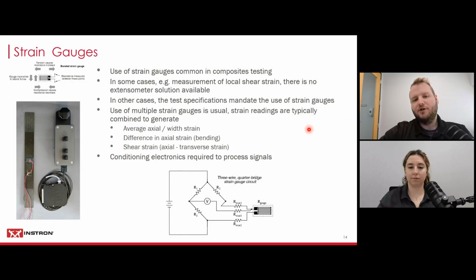Strain gauges, which I'm not too surprised that most of you are using, because they are required in many instances. So strain gauges are very common in composite testing specifically. I don't see that really being used in too many other material applications. And we covered some of those reasons earlier already. But in some cases, there's really no other solution available, either because the testing standard requires it, or because of the testing fixture that you need to use, for example, in compression testing of your composite materials, won't allow you to use a traditional clip-on extensometer. There simply won't be enough space.